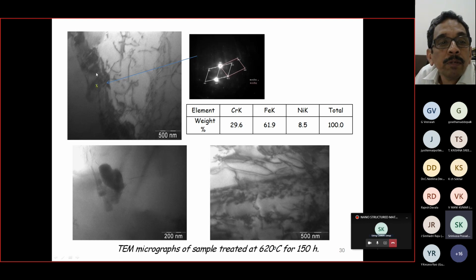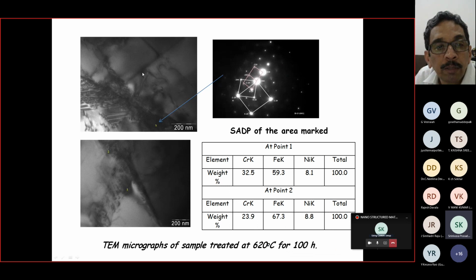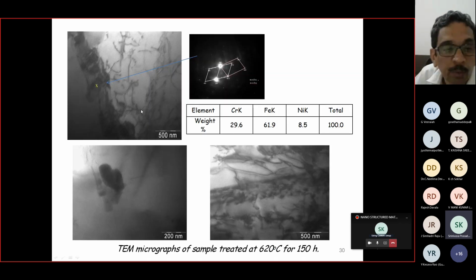Okay, and here also we were able to see, you can see that this, if you can put this micrograph in the previous one, there is some sort of a difference. Mind you, I have gone at a bit lower magnification. This is a 200 magnification. You can see that this is light. If you try to remember the previous slide, here at the 200 magnification, you are seeing a very dark region, but here at the 200 nanometers range, you are seeing very less intense or less dark areas. That means to say that chromium is depleted to a lesser extent over here. That means the heavier element is less in this. So this is what we try to understand the compositions.